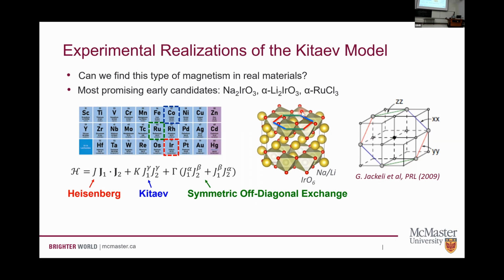So even though in theory we should get this perfect cancellation, real materials we don't expect to necessarily behave like model materials. And so even though we're looking for materials where this Kitaev interaction dominates, we expect that we might find some Heisenberg terms in here as well, our normal magnetic exchange. And also, if there's direct overlap between the iridiums, we might get these other magnetic interactions as well, things like symmetric off-diagonal exchange, sometimes called this gamma interaction.